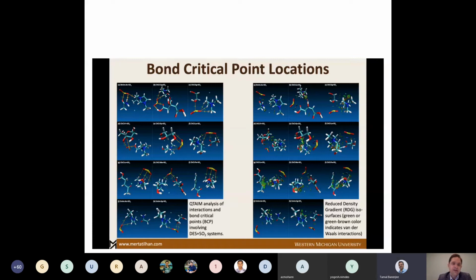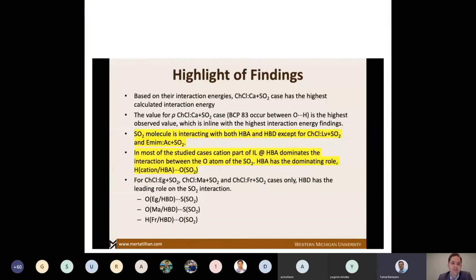how SO2 is in contact with which active site of the hydrogen bond acceptor or hydrogen bond donor. Not only that, we quantified the interaction strength, but on the right hand side, we were also able to draw some isosurfaces to observe the type of interaction, whether it is hydrogen bonding, Coulombic interactions, or van der Waals interactions, etc. So this was a very nice tool to set up initially to understand how SO2 molecules particularly interact with the deep eutectic solvent.